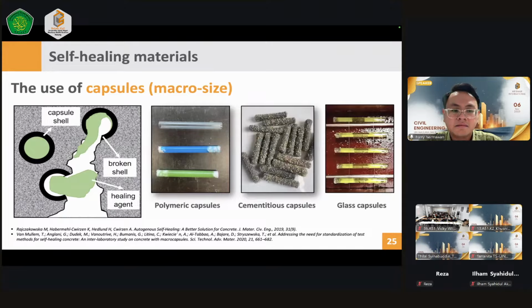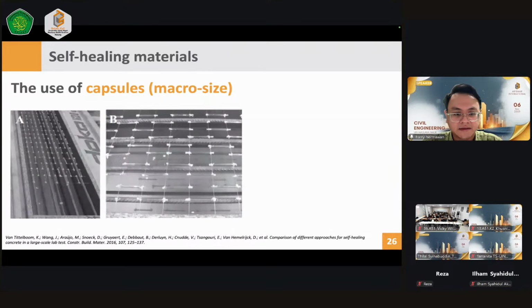But how can we place these capsules into our concrete materials? Well, I think the most beneficial part when we are using the macro capsules is placing them in the cover zone of the concrete. This is also an example from my colleagues. They are placing the capsules in the network of wire at the cover zone of the concrete, because the cracks will start from the surface, and the cracks will penetrate first of all into the cover zone of the concrete. So the location of the capsule is very important. That is why they place them in the cover zone, to let the cracks enter, and the capsule will break, releasing the healing agent into the cracks.